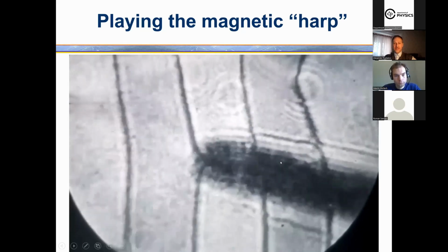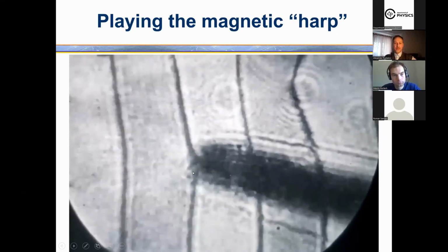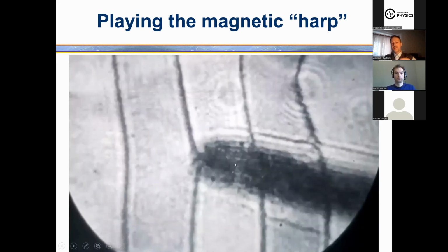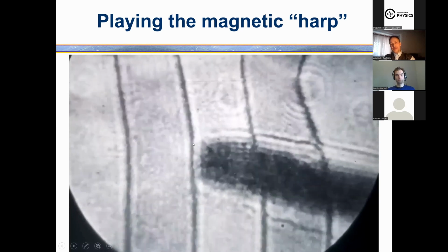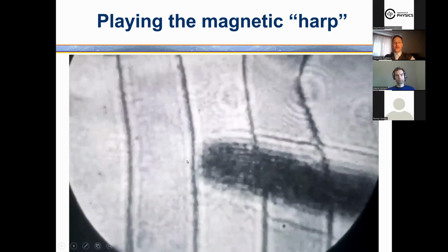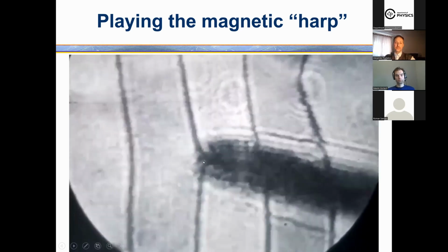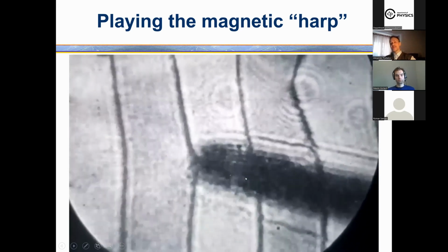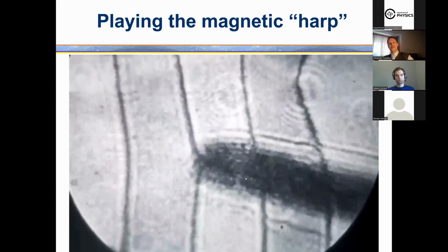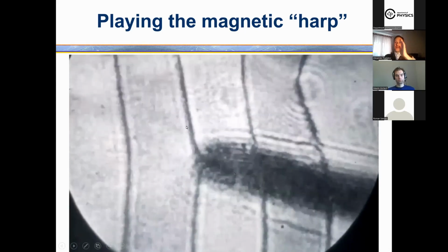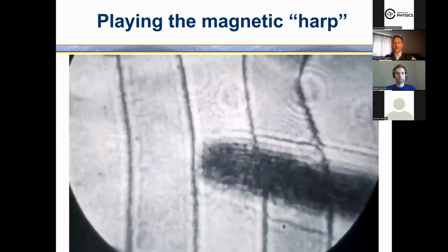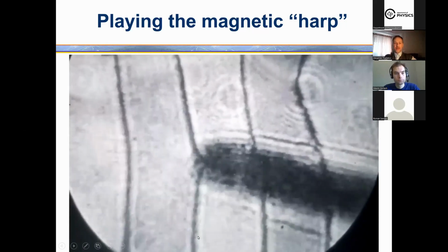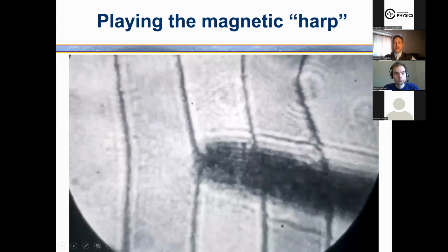And you can see here the electrode tip, and when we apply electric field to it, the nearest domain wall is attracted to the tip. And when we apply negative bias, the domain wall is repelled from the tip. So it's an electrically controlled magnetic domain wall, just because locally it became ferroelectric, local multiferroicity in magnetic media, just at the domain wall.